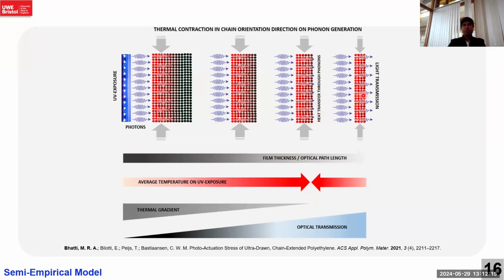But as soon as we move forward, making it much thinner at a higher draw ratio, the light passes through the material without being utilized. For example, the photon energy is not being utilized properly. So there should be a balance between all these parameters, like the concentration of BZT, the light intensity, the film thickness, and also the Young's modulus of polyethylene and its coefficient of thermal expansion.